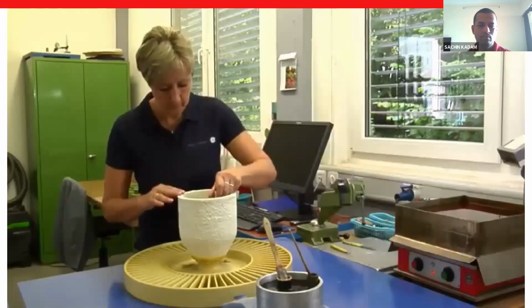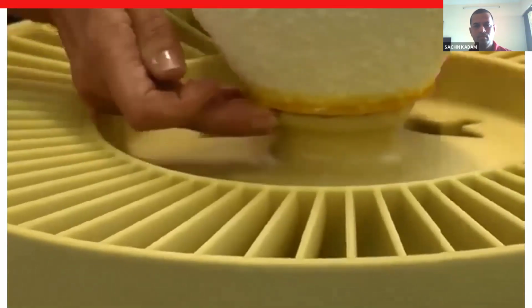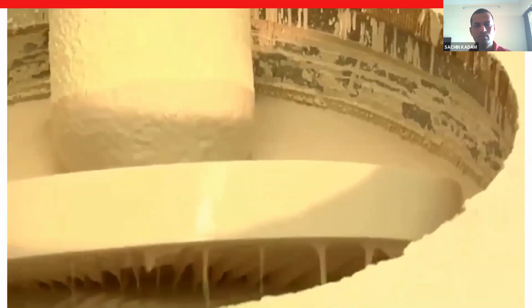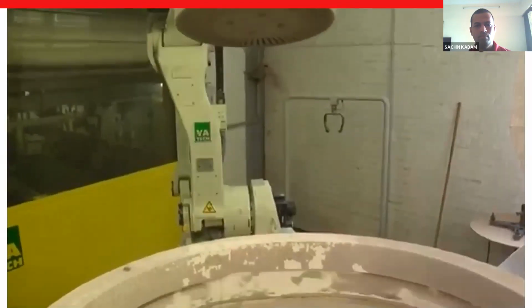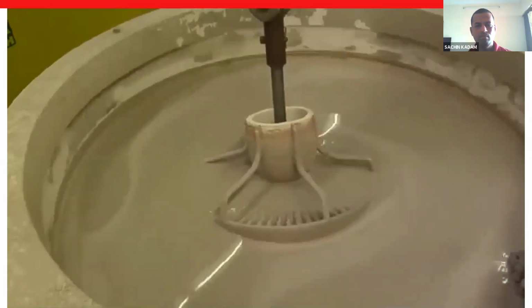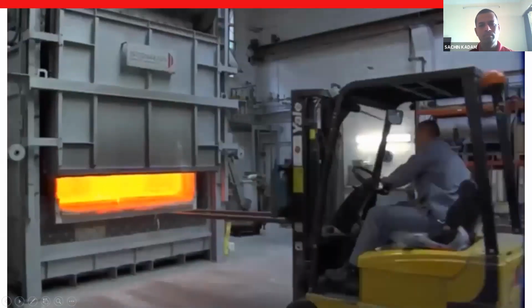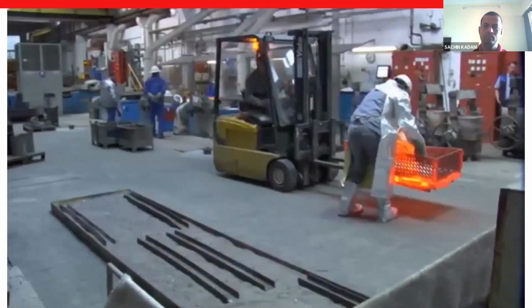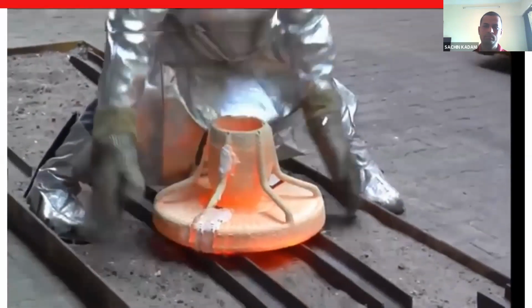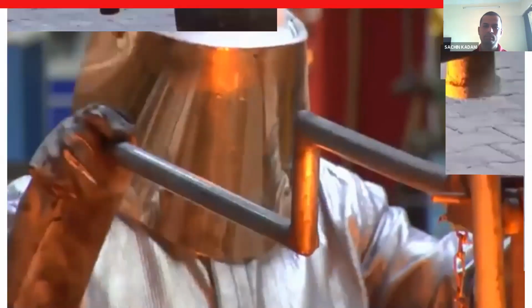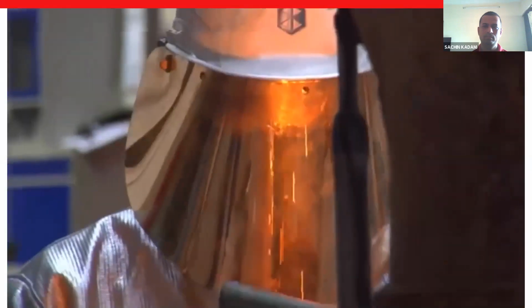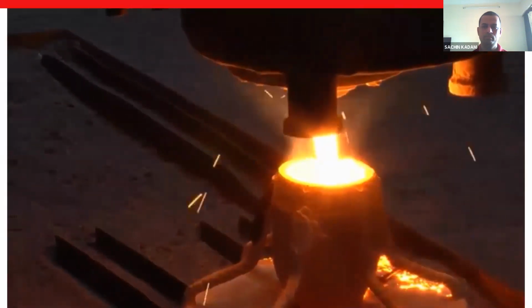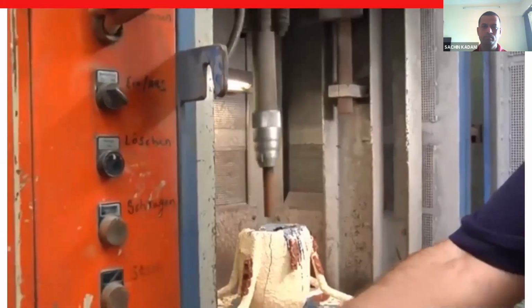The finishing process is the same as for conventional wax models. The first ceramic coatings are applied manually, while subsequent layers are added by a robot. The plastic models soften at 80 degrees C and shrink, so that tears cannot form in the ceramic shell. Finally, the 3D printed model is burnt out from the casting die in the kiln. The plastic models burn out with virtually no residue. Now the liquid steel, which is around 1600 degrees C, can be poured into the heated casting dies. The castings are removed once the molds have cooled.